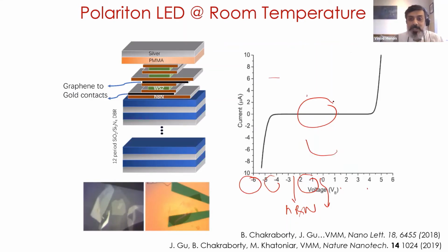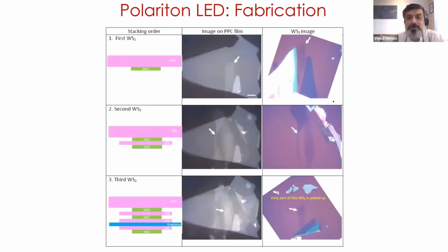And in fact, if you look here, this is the IV characteristics, and you can see they are the typical IV characteristics one would expect. Just to show you how this device looks, of course, they don't look beautiful at all. These are all exfoliated, so you have no control over the shape of the crystal that you're exfoliating. But you're starting with a boron nitride layer, and then you're picking up different layers and stacking them up, creating this completely electrically driven device.